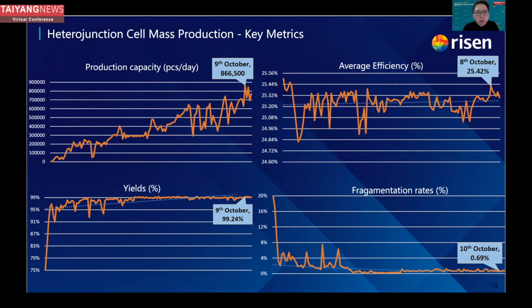And these are some key metrics we have observed from this October: production capacity for the cells has reached 866,000 pieces per day, the average efficiency has reached 25.42%, the yield rate of the solar cell structure has reached 99.24%, and in mass production of the cells the fragmentation rate is lower than 0.7%.